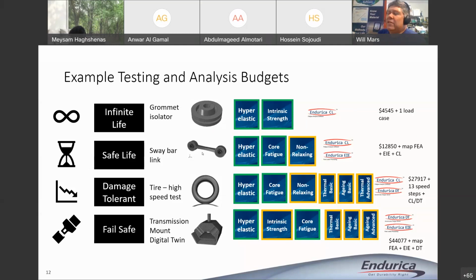Another part would be a sway bar link. This is a component of an automotive suspension. And the automotive OEMs will typically give you a target life that you need to hit. So Safe Life is what you're going to want to do here for a sway bar. A good example of the damage tolerant approach is in the tire specs. I mentioned there's government regulations when you sell tires. There's a test called the FMVSS 119, and it's a test that tires have to pass. It's not a test at a single load case. It's actually a composition of a series of load cases. And so it's necessary to be able to simulate that series of load cases and simulate how the damage evolves under those different load cases in order to check your tire design.